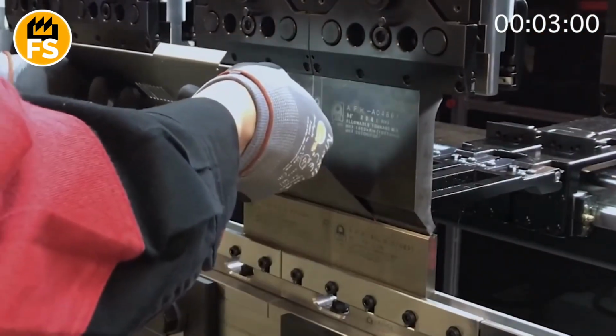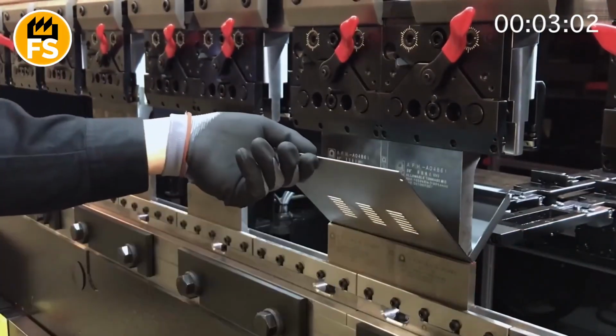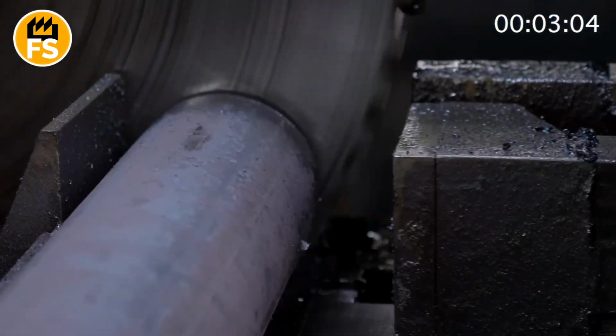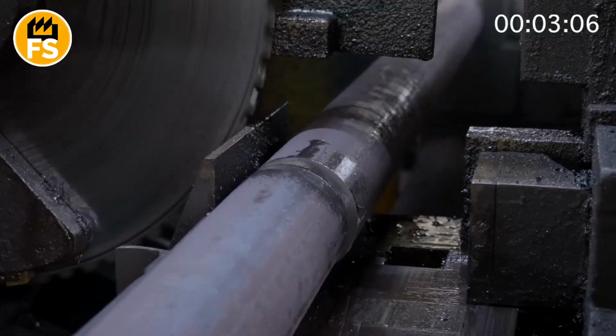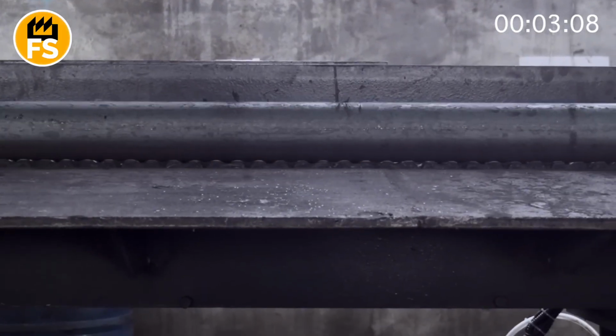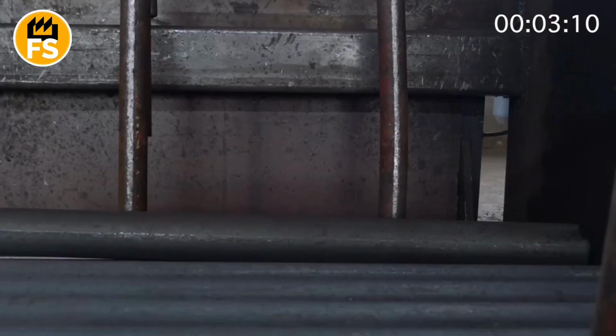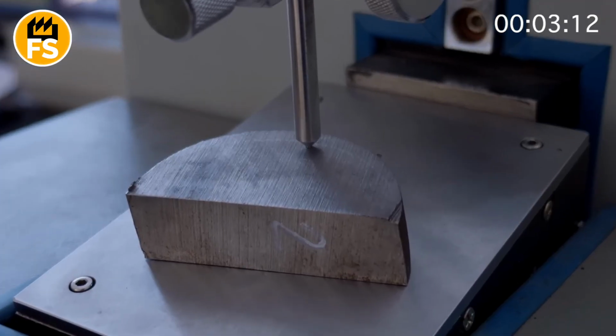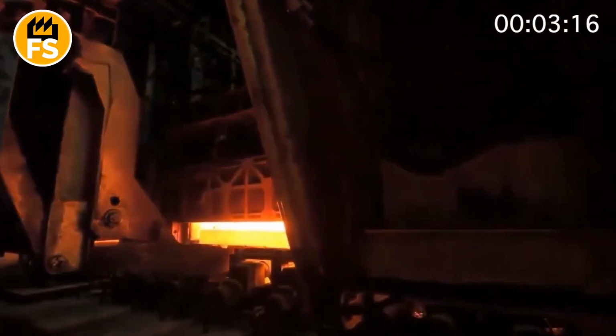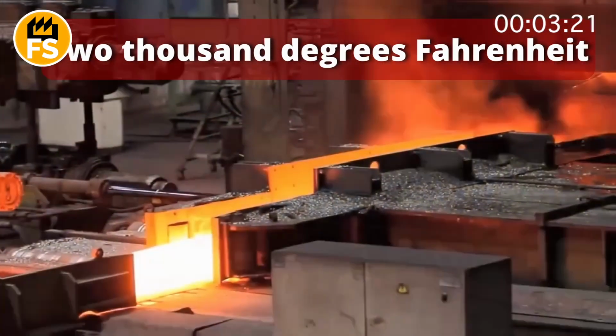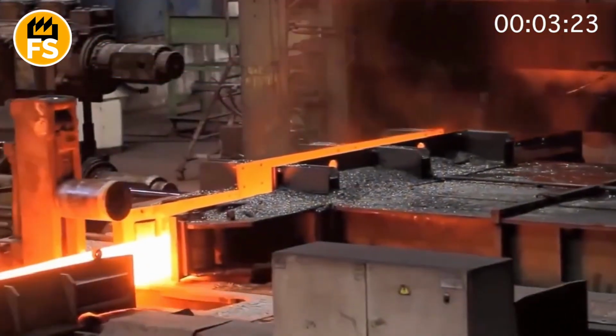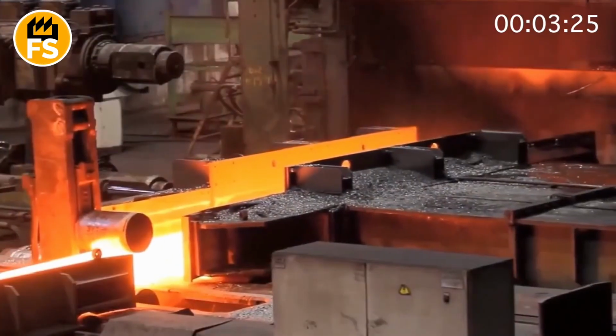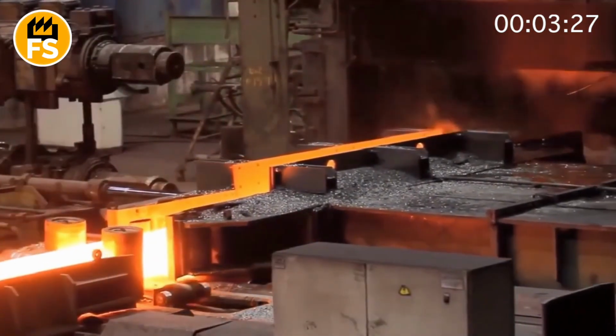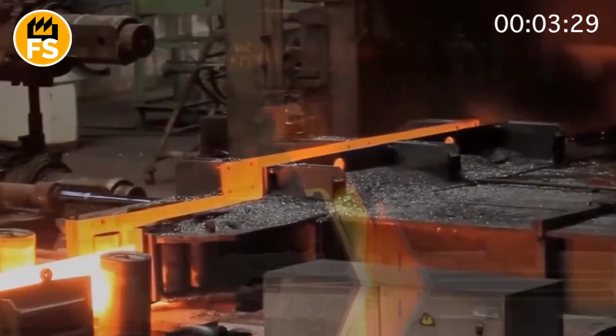Each cut piece falls onto a conveyor or into a basket, where it is automatically checked by a laser scanner. If the system detects a deviation in length or an uneven end, that piece is sent back for remelting or trimming. The pieces that pass inspection are moved on to heating furnaces, where a bright orange heat of over 2,000 degrees Fahrenheit awaits them. This temperature allows the steel to soften without losing its structural properties. It is there that the steel will become pliable and ready for bending into links.